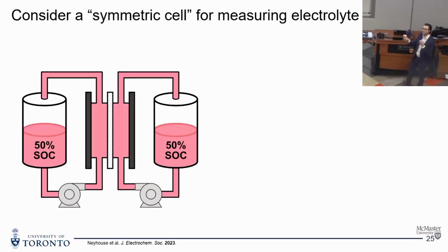So we start at 50% state of charge. So we have equal amounts of A and A+, for instance. And we charge one of these up to 100%, one of these down to 0%, and then we rock back and forth. So we can put the species in its unfavored state and see how the capacity fades over time. We design this cell in this way so that we eliminate the impacts of crossover.